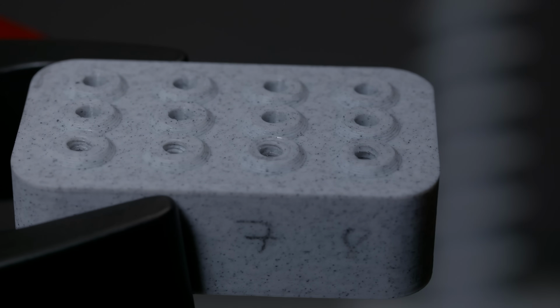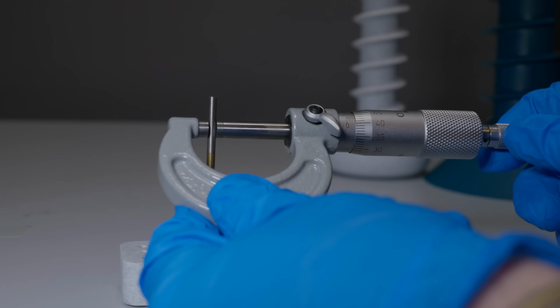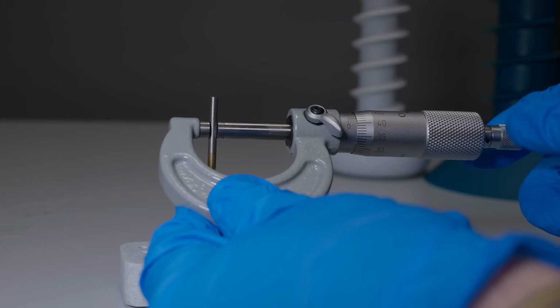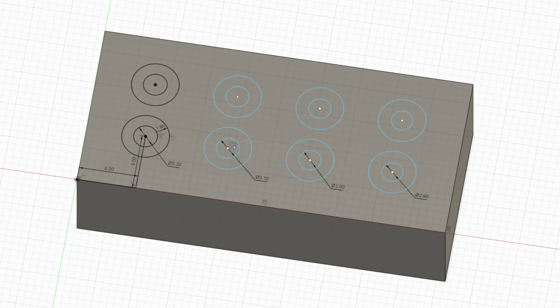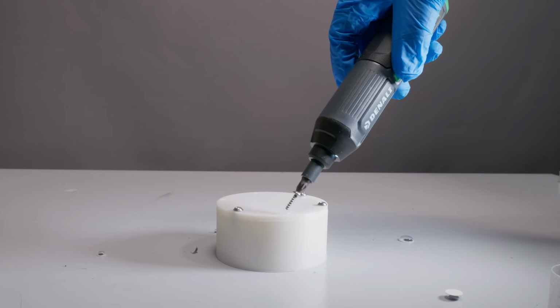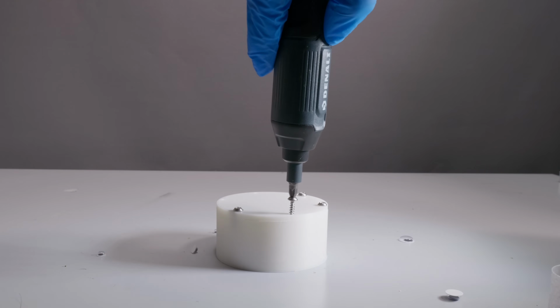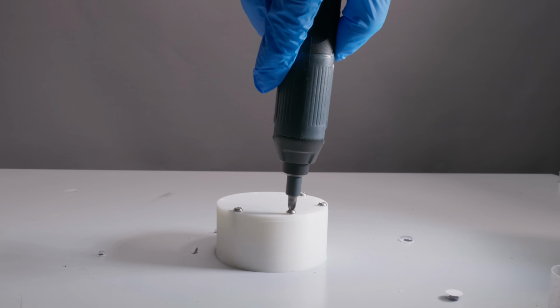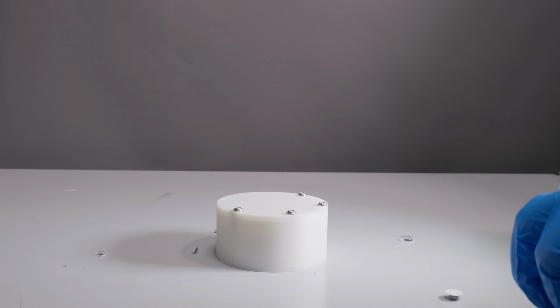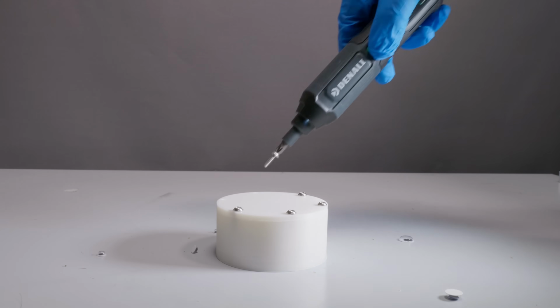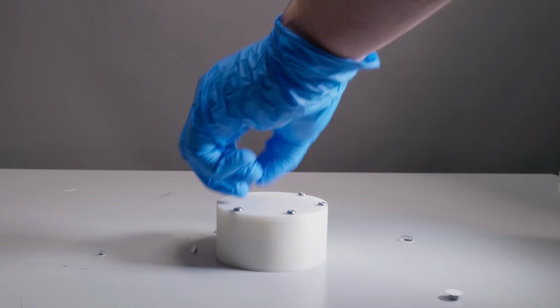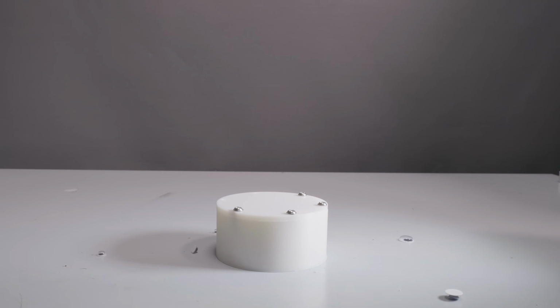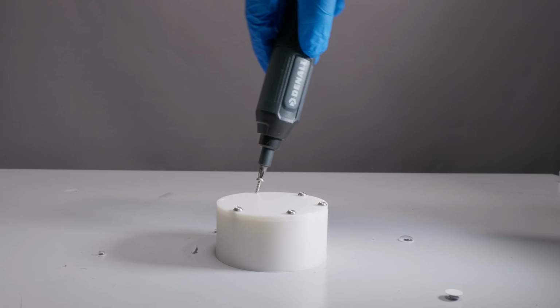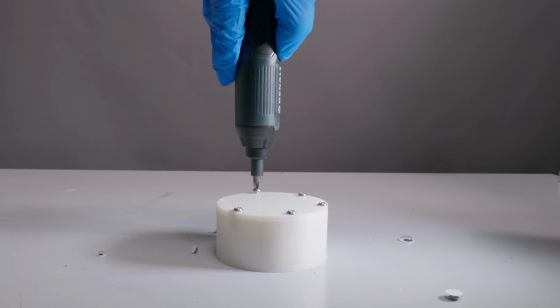So the process would be: measure your drill bit, see if your drill bit fits, and then calibrate for that and work out a factor. And then you should get a hole about the size that you are expecting. In my samples that I printed horizontally with the holes facing down, a 3.2mm hole in the CAD drawing turned out to be about 2.95mm in reality, which just happens to be perfect for a very tight fit for PLA with an M3 screw. But I also tested around those values to see the actual marks of the thread.